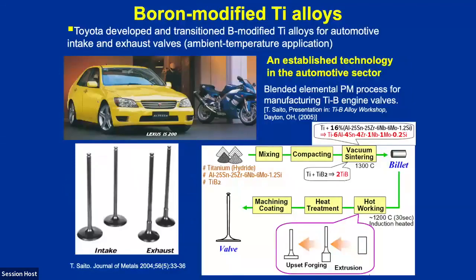The grandfather of boron modified titanium is Dr. Saito in Japan, who really pushed forward this technique in the early 2000s, so that it's in the automotive industry for sure. It's in the Altezza as an intake and exhaust valve. He started with a blended elemental powder metallurgy process for manufacturing these engine valves. He walked through the blended elemental technique with these powders: we mix them, compact them, vacuum sinter them, traditional powder metallurgy technology, make a billet, then hot work it, heat treat it, and machine and coat it.